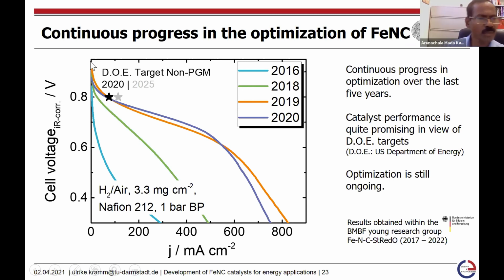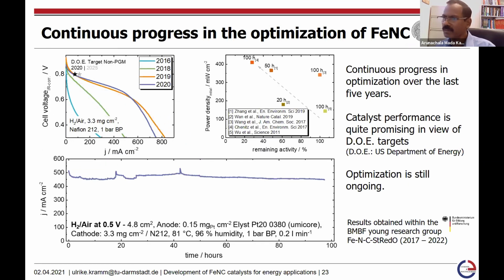Then I also wrote another one. It was mostly on the long-term stability. I think you had probably next slide, yeah, that's the one actually at the bottom. So you have 100 hours operation, and actually this is at 0.5 volt. But if you look at the data on the upper top left, at 0.5 volt, the current density is higher.